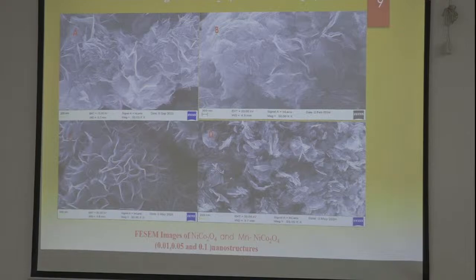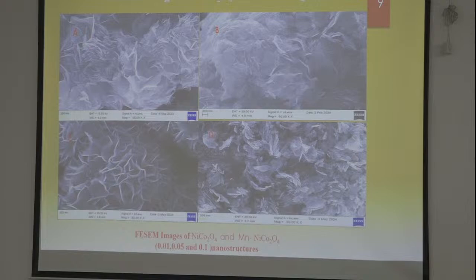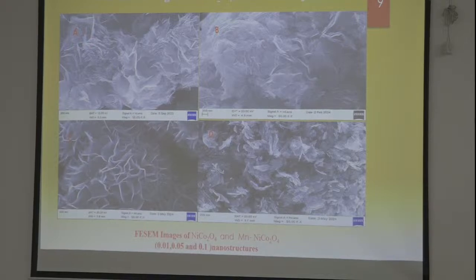This is the FE-SEM images of nickel cobalt oxide and Mn doped nickel cobalt oxide. This clearly shows that A represents pure nickel cobalt oxide, which gives a nano flake-like structure. When I added manganese dopant at 0.01 molarity, it gives a nanosheet-like structure. C represents 0.05 molarity ratio, giving a flower-like structure, and 0.1 molarity ratio of manganese doped nickel cobalt oxide gives a leaf-like structure.